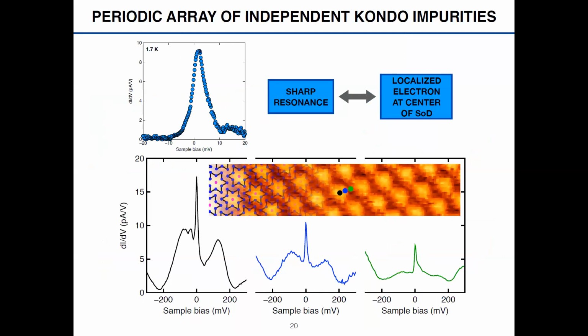So this zero bias peak, this Kondo resonance, is modulated spatially. Its intensity is modulated spatially with the periodicity of the 1T charge density wave. So it's more intense in the center of the Star of David, where this unpaired electron is localized, and its intensity is reduced as you move away from the center of the charge density wave. So we believe that therefore this peak is related to this localized unpaired electron.